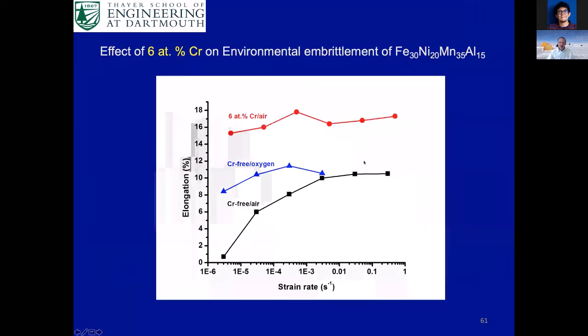So we took the 6 at.% chromium alloy, which showed the best ductility on the previous slide, and we tested that as a function of strain rate. You can see here are the results. When you add that chromium, not only do you get over this environmental embrittlement, but you've also improved the ductility of the material as well. You can see here we get about 17% elongation or so, compared to about 10, and we get that roughly at all strain rates.